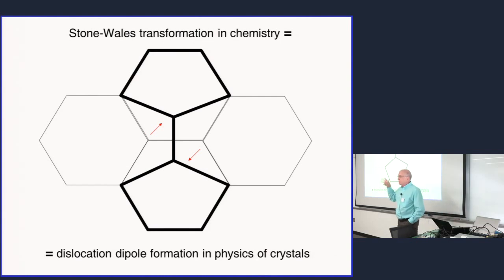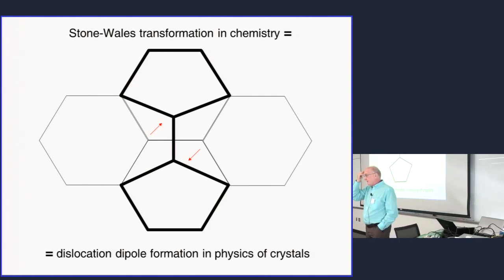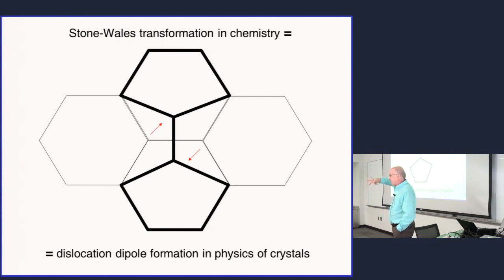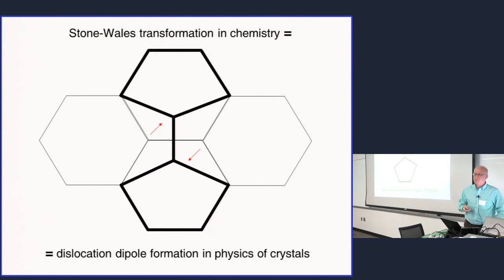Interestingly, this transformation was well known in the chemistry of fullerenes as the Stone-Wales transformation. You just flip a bond 90 degrees, and for chemists, it was isomerization of fullerenes. This is an isomer. If you have a cage, you just create many isomers by flipping these bonds one after another. And for C60, I believe you can create almost 2,000 isomers. So this slide is as simple as it is, but in a sense very important because it bridges the world of chemistry, the isomerization process, with the world of mechanics of materials, or physics of crystals, because at the same time it's a dislocation dipole which can be created in the lattice.